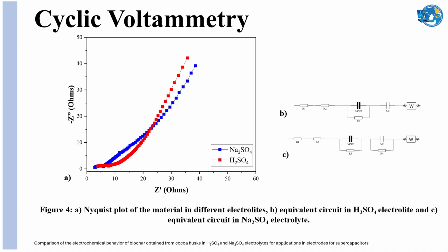The analysis by electrochemical impedance spectroscopy in both solutions allows for a better understanding of the electrochemical processes that explain the electrode performance. To this end, equivalent circuits were modeled, initially including two clearly differentiated resistances, one associated with the electrolyte resistance and the other with the electrode-electrolyte interfacial resistance. This highlights the combined influence of ion transport in the medium and the kinetics of charge transfer at the electrode-electrolyte interface. Subsequently, a constant phase element was found to present a non-ideal capacitive behavior that explains the angle present in the graph.